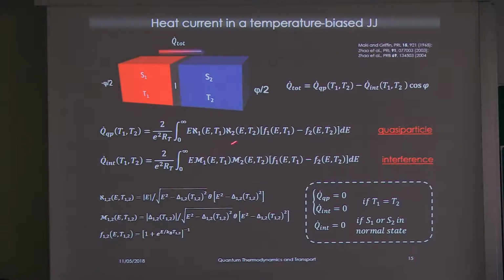I will not go into detail on this, but in analogy to the quasi-particle part, this is expressed in terms of the density of Cooper pairs in one part and in the other part, times the difference in distribution function. What is important to recall is that if the temperatures are identical, of course, there is no heat current in the system. You can say, okay, this is trivial, both of them are zero. But the interference part can also be zero if one of them is in the normal state. So there is another condition you need: both of them must be in the superconducting state and there must be Josephson coupling. This is important because without Josephson coupling, you have no phase-dependent part. The phase-dependent part is basically the analogue of the charge Josephson effect in a purely current-biased Josephson junction.